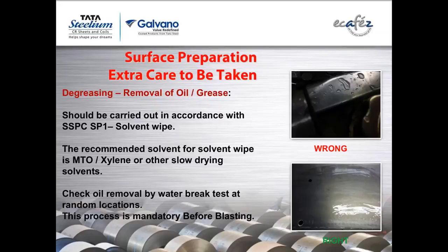Now, how to check it? A very simple test is you can have a water bottle with a spray, like the barber has. Spray it on the surface. You can see the photographs on the right. The top photo will show shrinkage of water, which tells you that oil is present. In the photo at the bottom, you will find a clean film of water, which gives you an indication that oil has been removed. If you don't remove the oil before blasting, the grits are going to push it inside the depth, which is going to give you a problem in future.